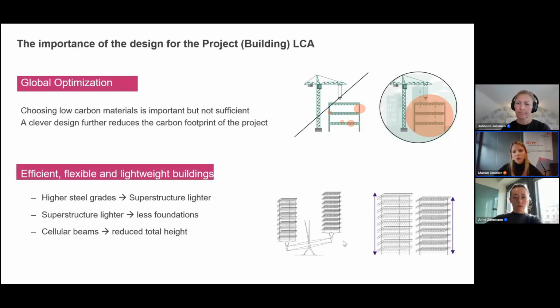So for example, when it comes to steel structures, quite simple but yet effective measures would be, for the members where it makes sense, to use high steel grades. For example, for the columns, which are driven by resistance, then we're making the superstructure lighter. We need steel sections which are globally smaller. We have less material, and so we're making carbon savings. And we're not even talking about low carbon steel here. We're just making material savings. But on top of having a lighter superstructure, we will also have less foundations. So all of these things need to be taken into account as a whole, really having this holistic view of the project.